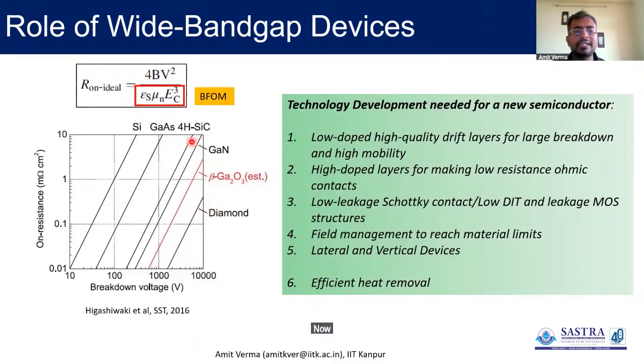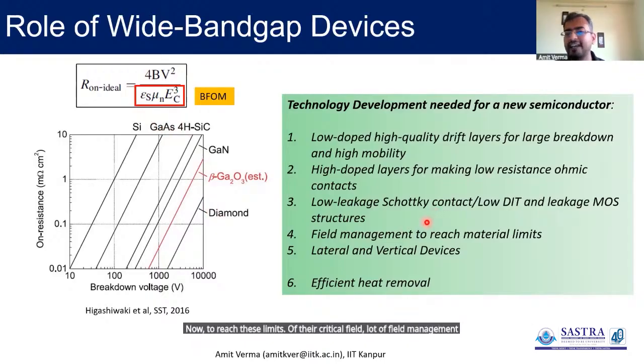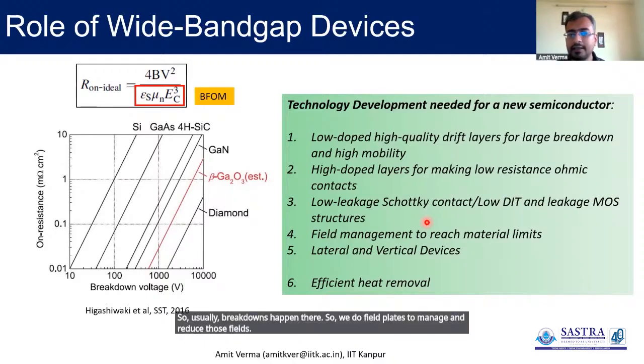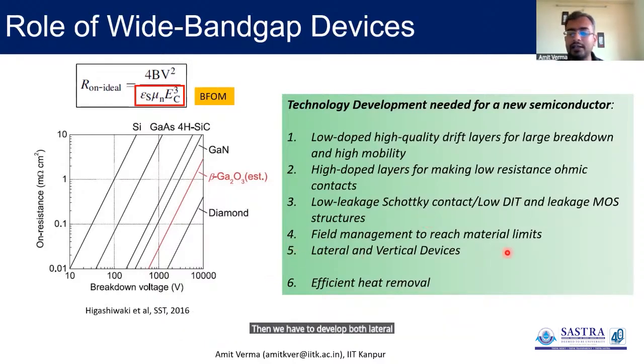Now to reach these limits of the critical field, a lot of field management has to be done. Field plates, RESURF. There are different techniques by which we manage the field so that we can reach these limits. Because once we have finite size devices, there are edge effects that play a part, where at the corners the electric fields are highest. So usually breakdowns happen there. So we use field plates to manage and reduce those fields. Then we have to develop both lateral as well as vertical devices because, again, they have their own advantages and disadvantages.